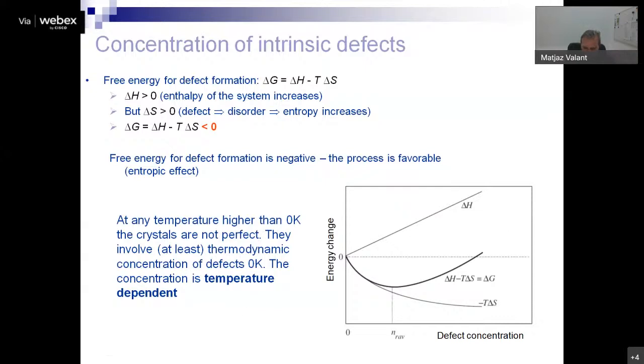So the consequence of this is that at any temperature higher than 0 K, the crystal has got some equilibrium concentration of the defects. And this equilibrium concentration of defects depends on the temperature, because this curve depends on the temperature. We have temperature here in this expression.